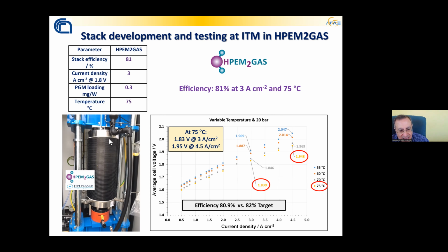So the black part you can see are the bipolar plates, because the MEA is extremely thin, less than half a millimeter thick, but the bipolar plates are a few millimeters thick. In this case, we have used - this has been developed by our colleagues at ITM Power in UK - in the framework of the project HPEM2GAS.